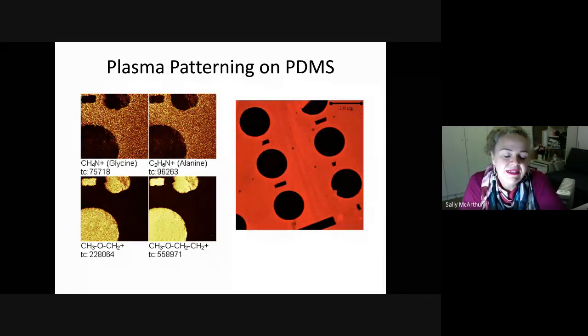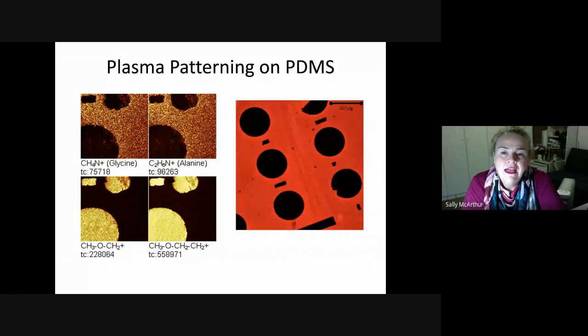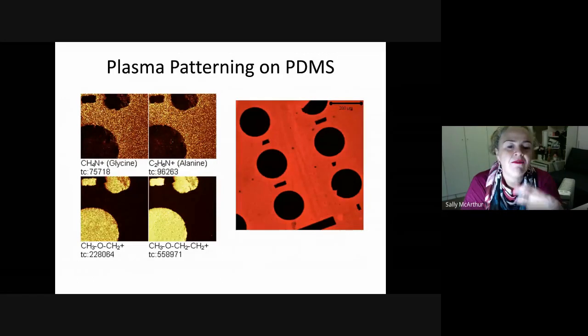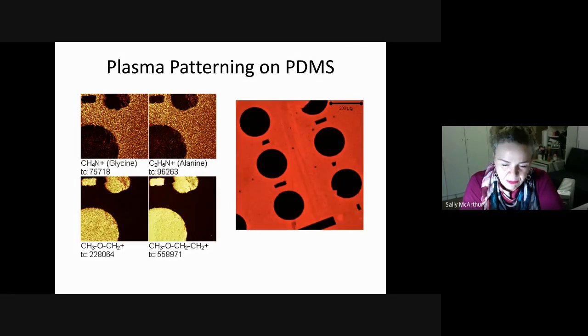But polydimethylsiloxane, or PDMS, silane-based materials are beloved of the bioengineering community because we can make devices and microfluidics out of them quite quickly. We get small-scale ideas tested. But putting plasma polymers on top of these silane-based materials or silicone-based materials is really hard because of the creep. So you have a lot of unreacted monomer, and we all know once we have silanes in our lab, we have silanes in our lab forever.